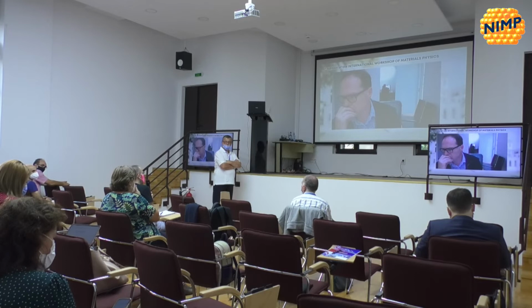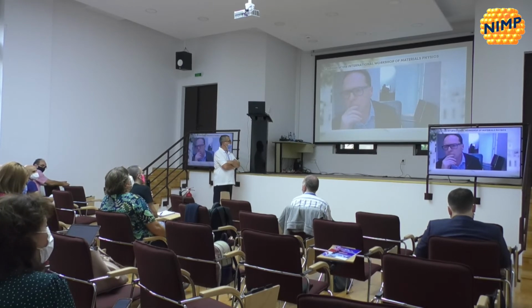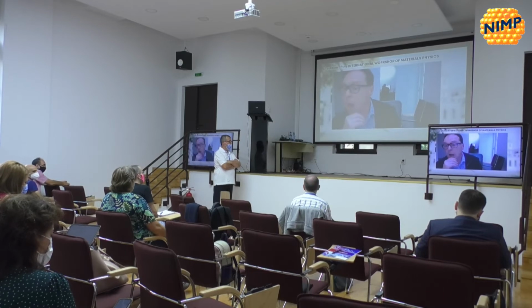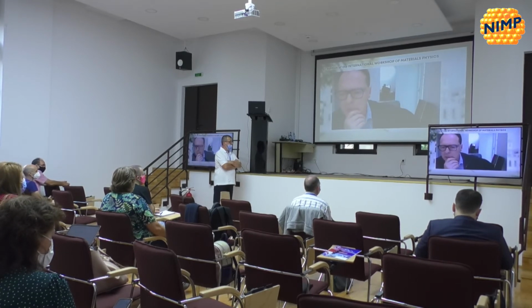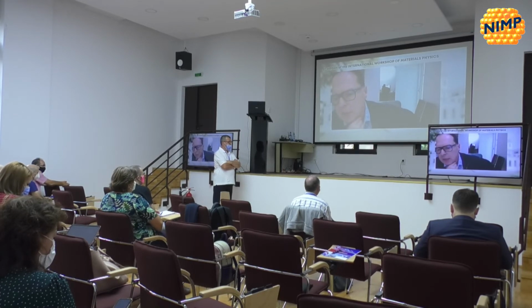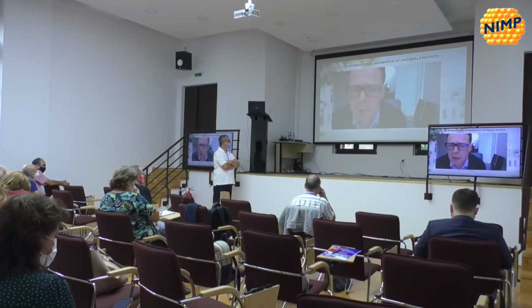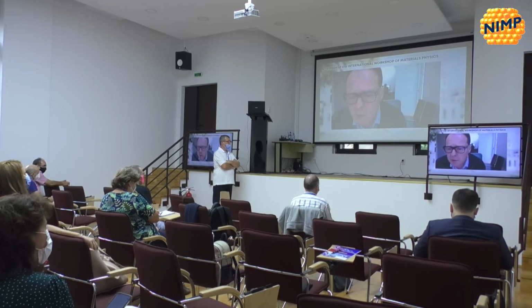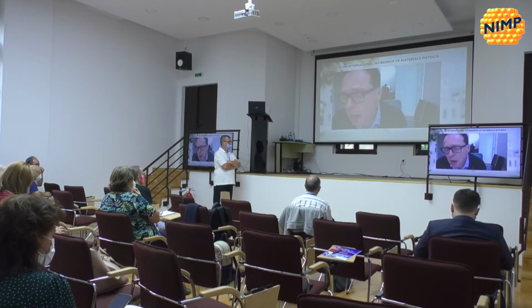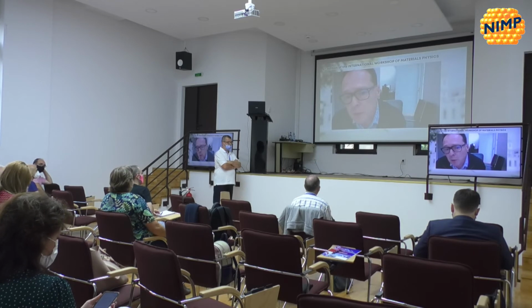Right, but it's very, very unusual, right? Because this domain wall, in principle, is very different from silicon. Absolutely. Crystalline silicon or anything like that. And I guess when you compare it to other 2D systems, that's where we got most excited. If you do a cursory look for things like Hall mobility in graphene and LAO/STO here, you get absolutely huge numbers, 80,000 and so on and so forth. But those are cryogenic temperatures, not at room temperature. And at room temperature, the mobilities are pretty modest. So I can't speculate, Jorge. I don't know what the physics is. I'm not going to pretend. I'm going to explore and see if we can find out more.